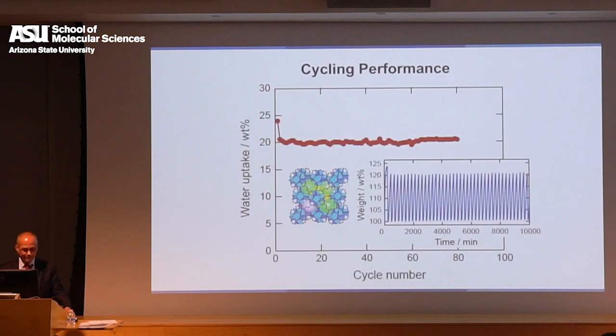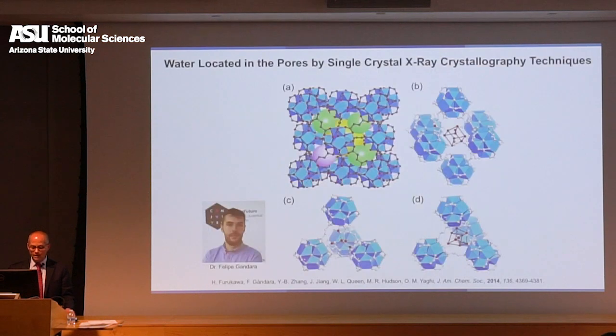And indeed, you can do this for many, many cycles, and the MOF structure is maintained, the performance is maintained. The only thing that we notice is that there's a slight drop in performance, or in uptake, after the first cycle. What was that? And now comes why we are working so hard to make crystalline materials. Aside from the obsession of Mike O'Keeffe and Omar Yaghi with crystals, there is a practical thing, and that is now we can dig into the structure and find out where those first water molecules are residing and what their interaction with the framework is.